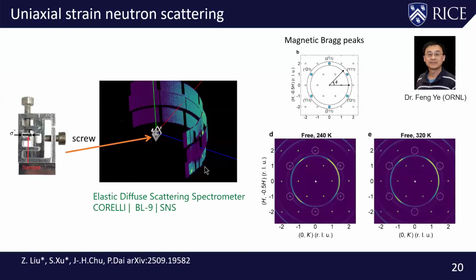And the first thing we wanted to do is to determine what is the true magnetic structure of the system, given that we know the moment is aligned in the AB plane. What we have done initially is to take a crystal cut into a square shape, and then apply uniaxial strain along either the nearest neighbor or the next nearest neighbor direction, using a force to exert a tiny amount of distortion, and therefore potentially change the 3 domain into a 1 domain within the AB plane. Then we can look at the diffraction patterns throughout the reciprocal space and determine, hopefully, which magnetic structure is actually correct.